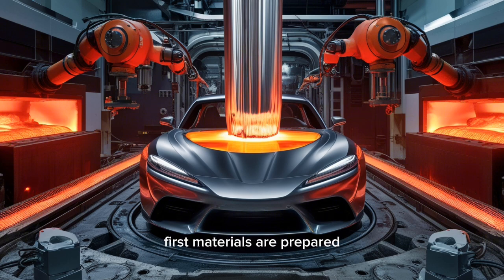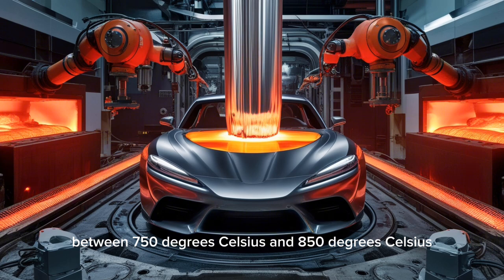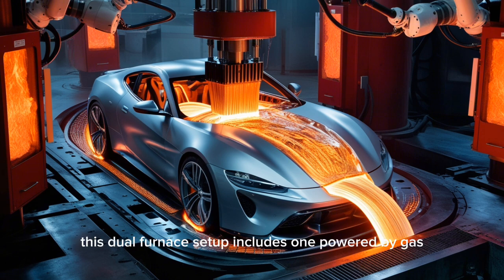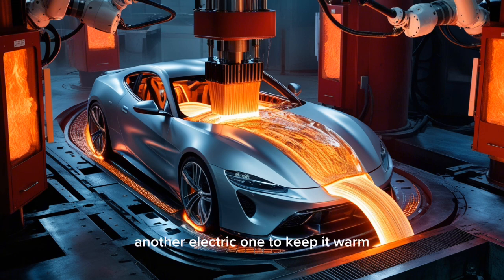First, materials are prepared. Tesla melts fresh aluminum along with leftover scrap in a furnace heated to about 850 degrees Celsius. After removing any surface dirt, the molten aluminum flows through heated pipes into a second furnace that keeps the temperature steady between 750 degrees Celsius and 850 degrees Celsius. This dual furnace setup includes one powered by gas to melt the metal and another electric one to keep it warm. Nitrogen gas fills the empty area inside the furnace to stop oxide formation and help keep temperatures steady. In addition, operators use argon gas, a rotary cleaner, and a special filter to get rid of more impurities and any particles bigger than 25 microns.